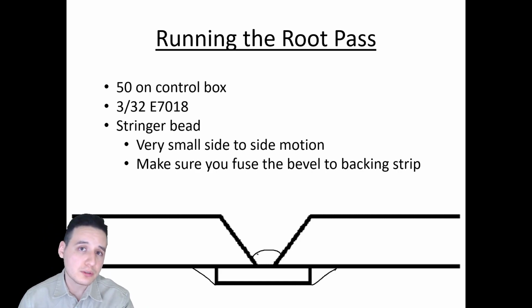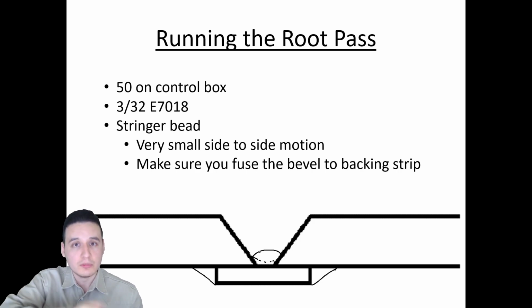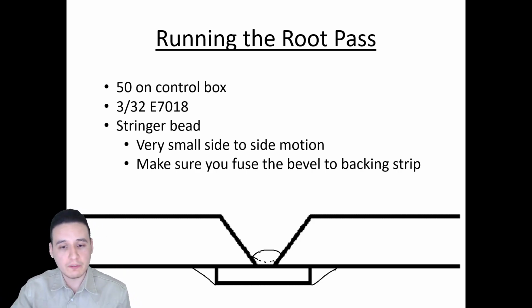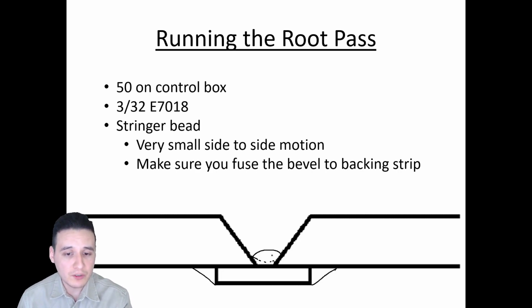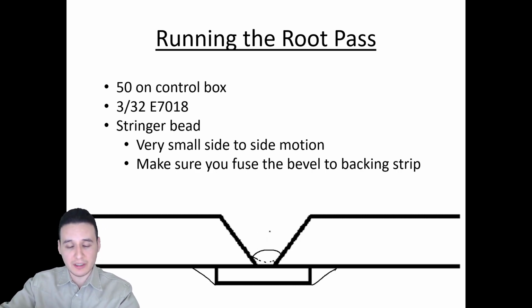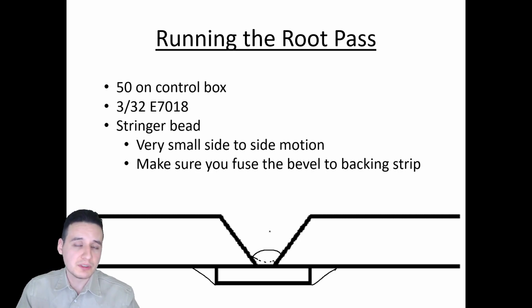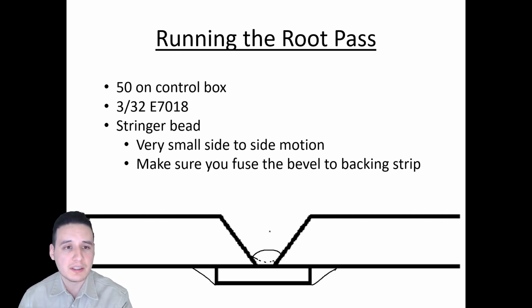And of course, you also don't want the opposite, to where your bead is concave either, where it's caved in on itself. You want it flat. If you don't have a good foundation with your root pass here, guess what? The other beads that you're laying on top of it are also going to come out bad, because again, the foundation is off. It's very similar to a home. And so keep that root pass as flat as you can.